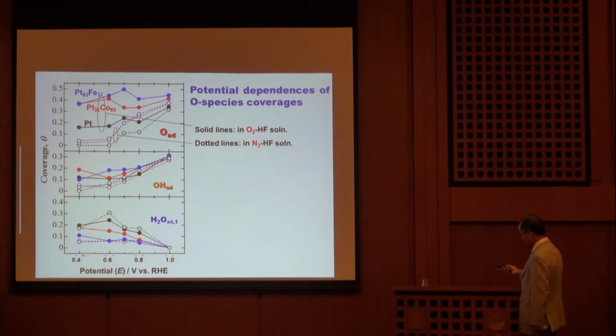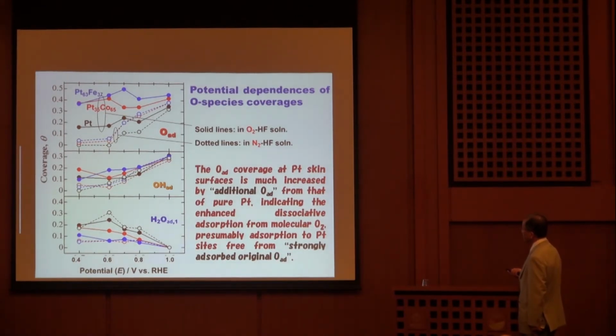In a similar manner, we determine the oxygen coverage on the platinum skin layer and also the pure platinum surface in an oxygen saturated electrolyte solution in comparison with the nitrogen saturated solution. The oxygen coverage at the platinum skin surface is much increased by additional oxygen adsorbed species from that of pure platinum, indicating the enhanced dissociative adsorption from the molecular oxygen, presumably adsorption to platinum sites free from strongly adsorbed surface oxide.